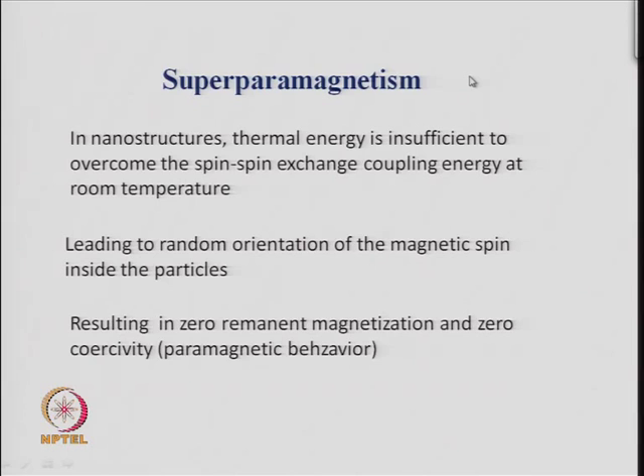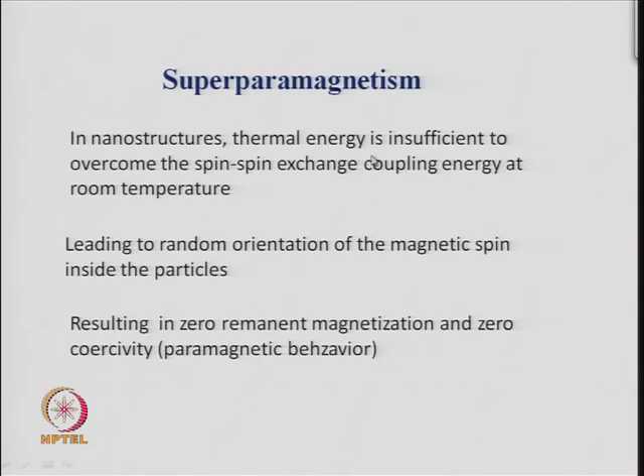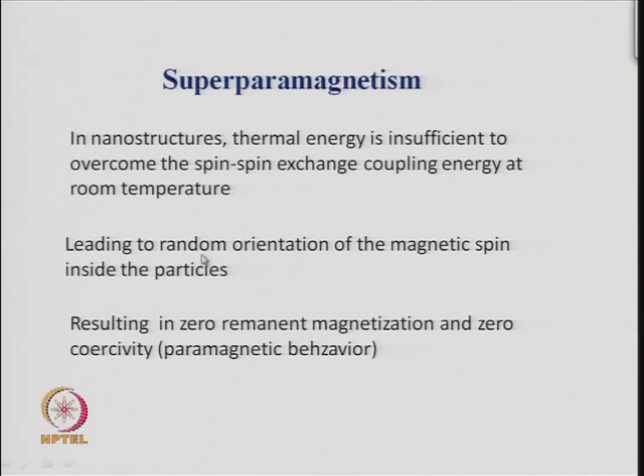Now, we come to the exact problem of magnetism in nanomaterials. What is superparamagnetism? Many of these magnets, when you decrease the size of the particle to the nano dimension, you will get superparamagnetism. So, in nanostructures, the thermal energy is insufficient to overcome the spin-spin coupling energy which exists between the magnetic dipoles at room temperature. So, they are unable to change their position. You won't have that kind of energy to overcome the spin-spin exchange coupling energy at room temperature. And if you cannot overcome that, then you will have a random distribution of the magnetic vectors. And that is what happens in superparamagnets, where you have a random orientation of the magnetic spin inside the particles.